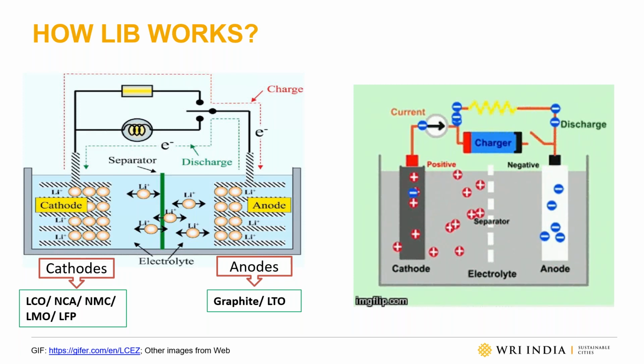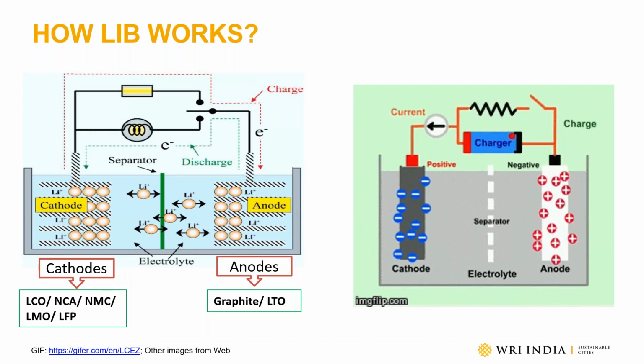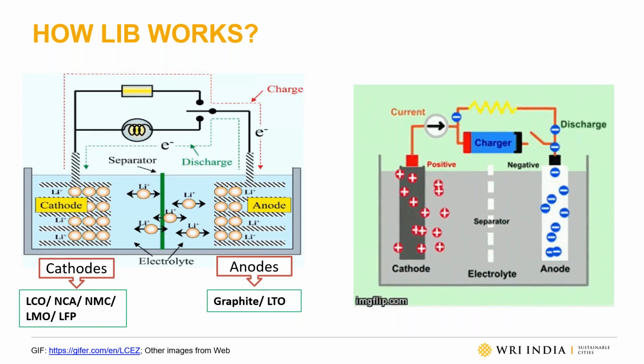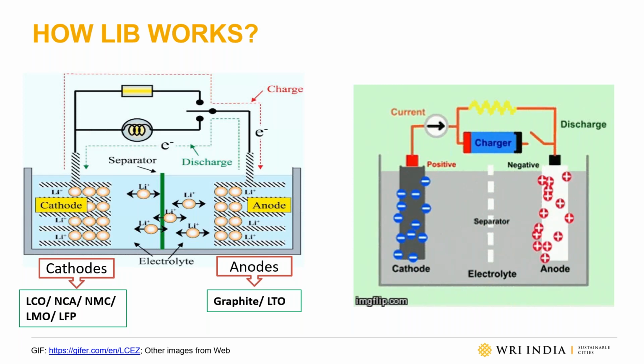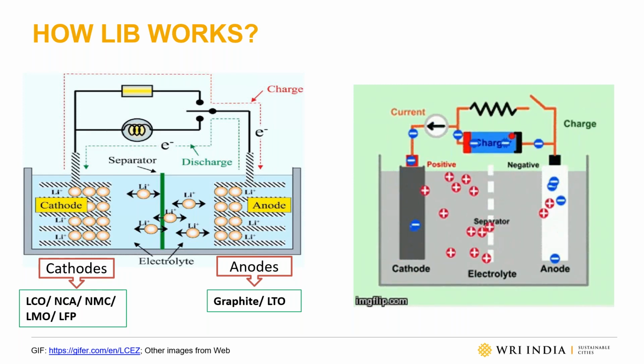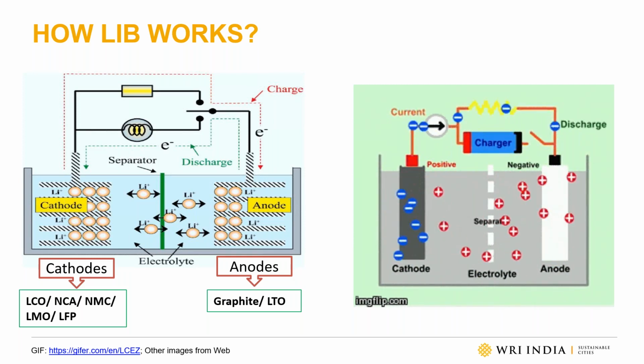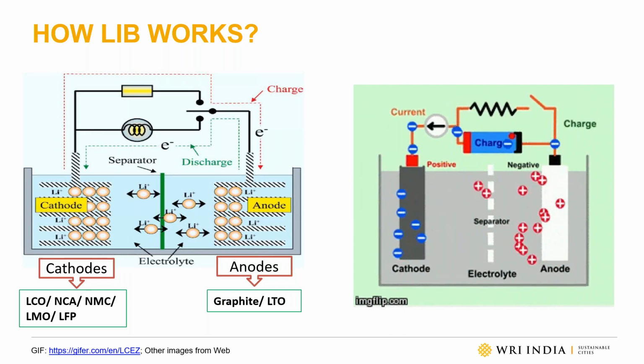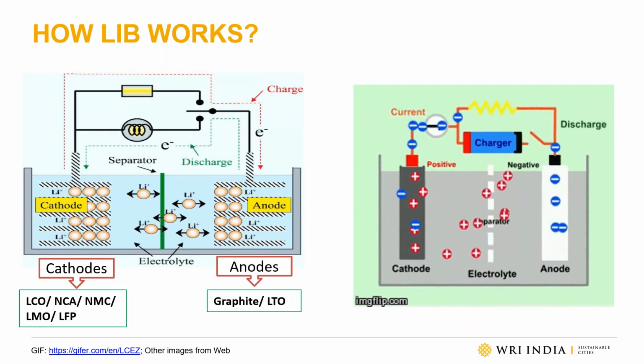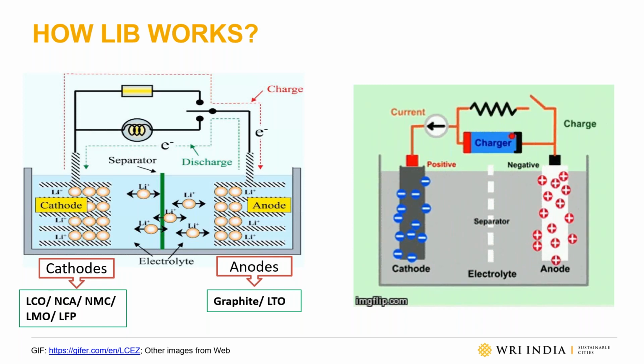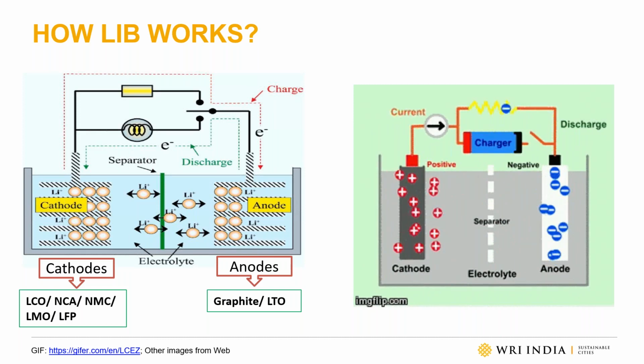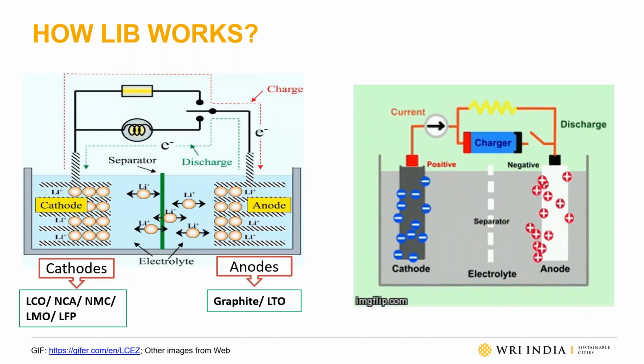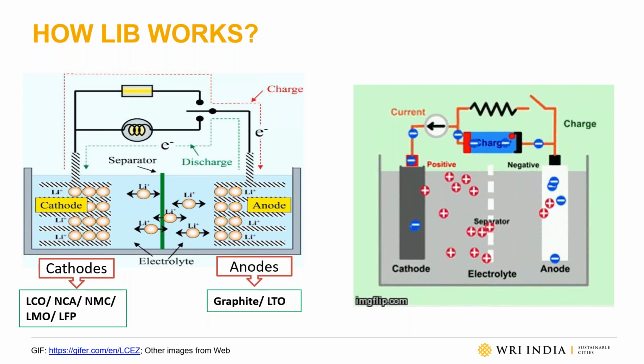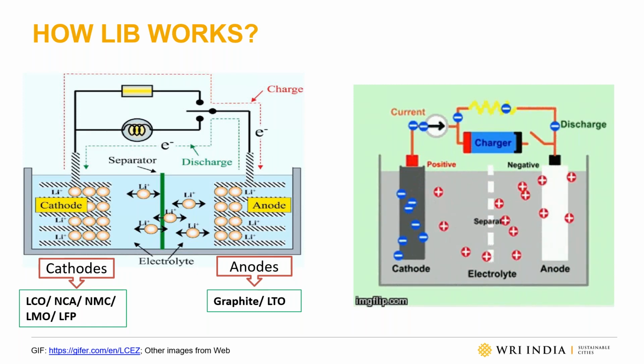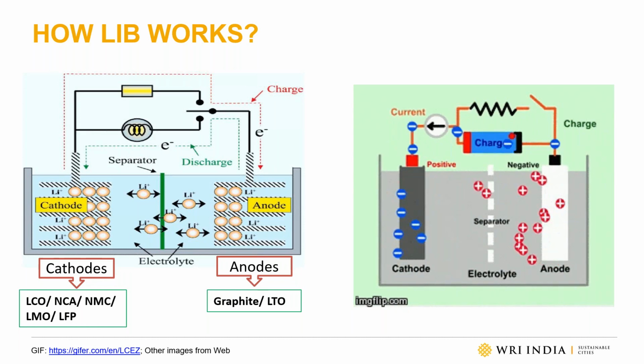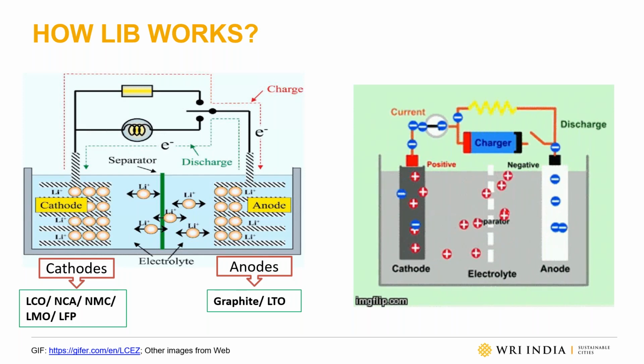In the case of lithium battery, we have several options on the cathode side. One is lithium cobalt oxide, which is mainly used in mobile phone batteries. Then we have nickel cobalt aluminum, that is NCA, nickel manganese cobalt, that is NMC, lithium manganese oxide, that is LMO, and lithium iron phosphate, which we call LFP. Mostly these cathode materials are used with one of the anode materials, that is graphite and LTO. Currently, graphite is the most preferred anode material in lithium-ion batteries. But each battery composition has some limitations. So based on the requirement and application, one can select the cathode and anode material.